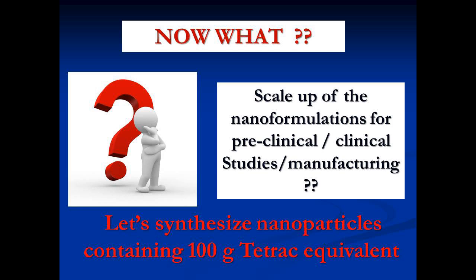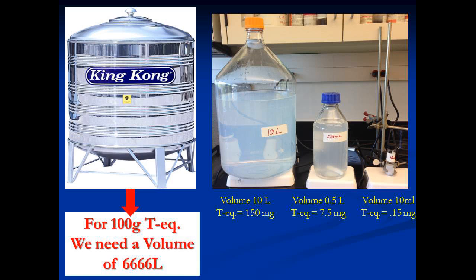Now what? How do we scale up this nanoformulation for preclinical study? Let's synthesize a 100-gram Tetrac equivalent of the formulation. What we started with is 10 ml in the lab, which gives us 0.15 mg Tetrac equivalent. When you go to half a liter, it gives us 7.5 milligrams of Tetrac equivalent in a nano formulation. For 150 milligrams of Tetrac equivalent, which is the API, we need 10 liters of liquid.